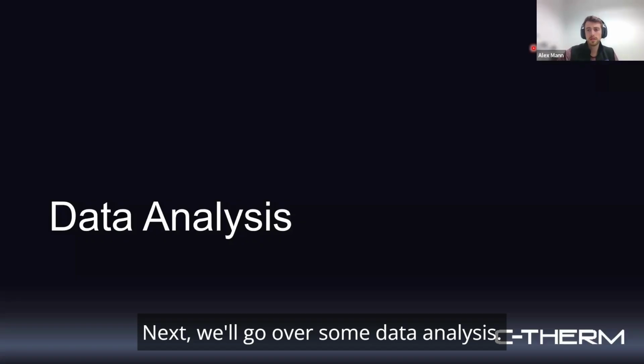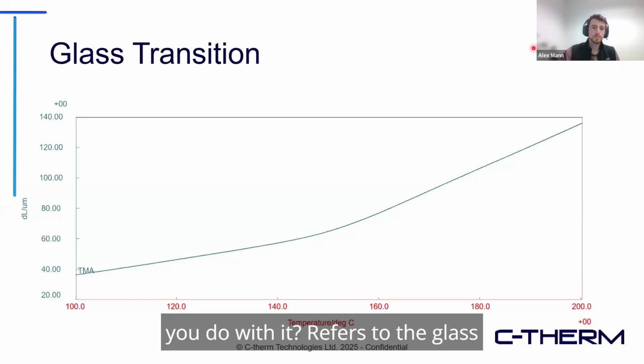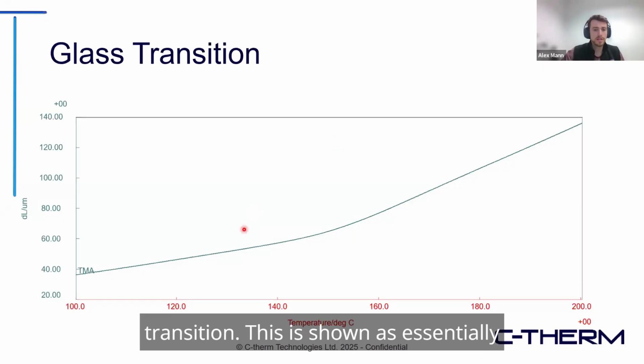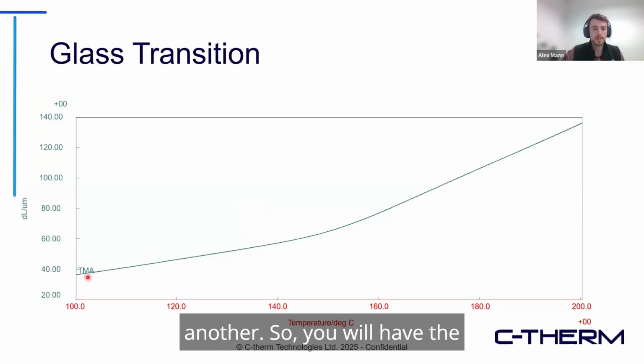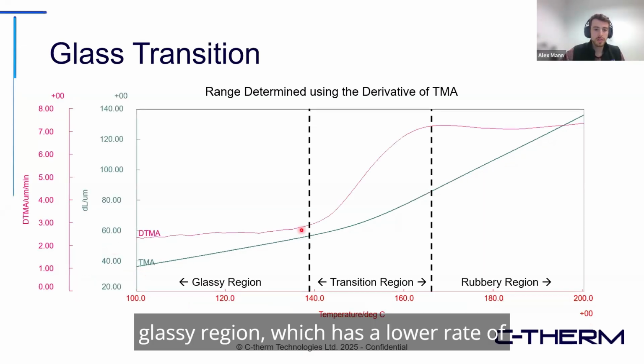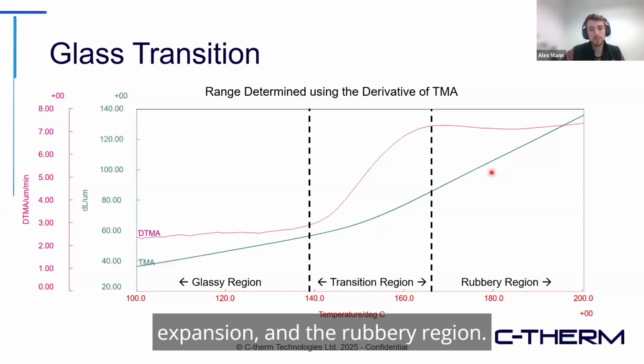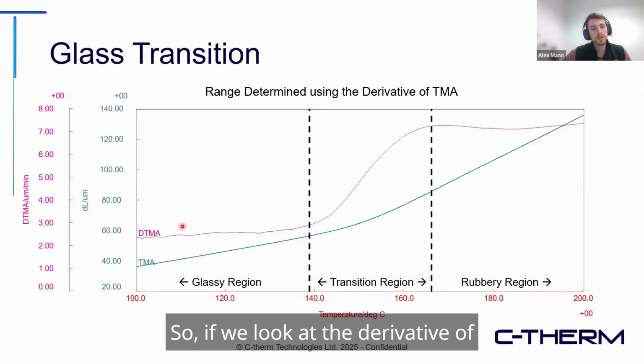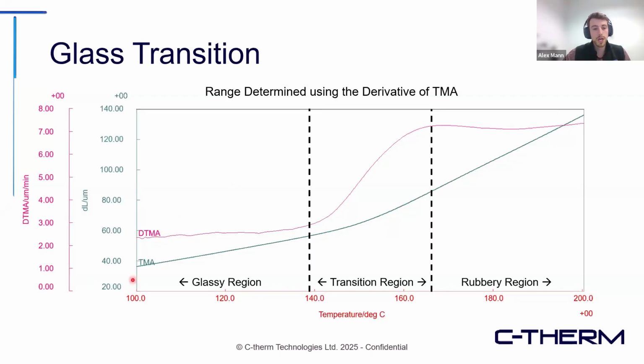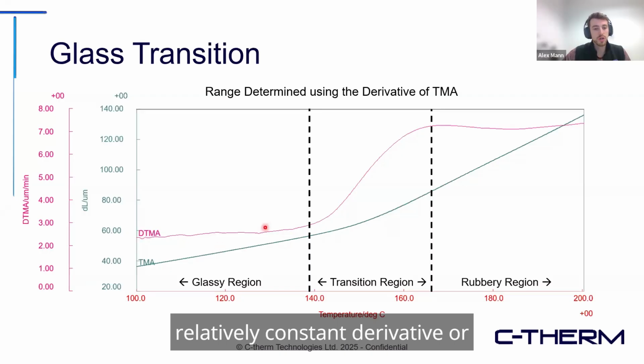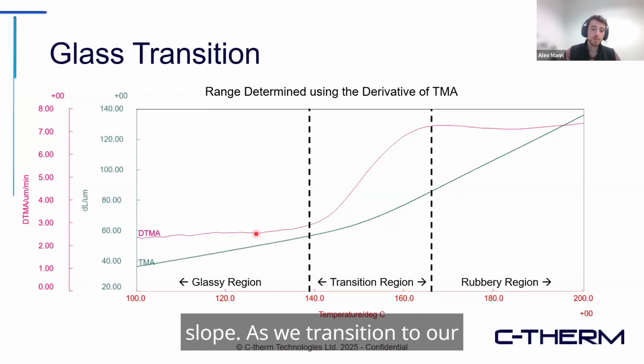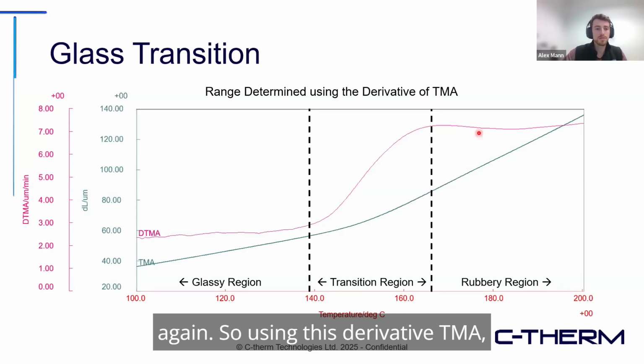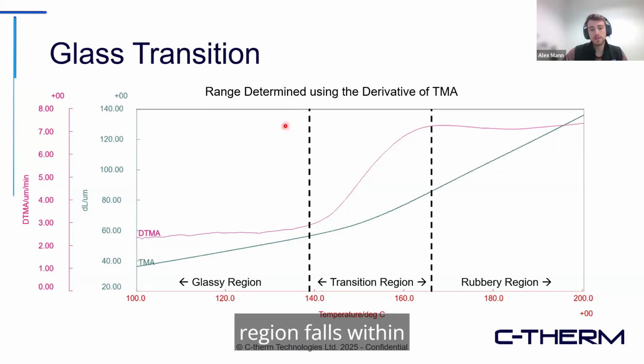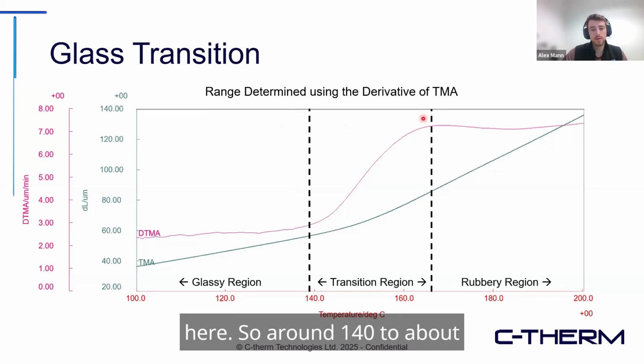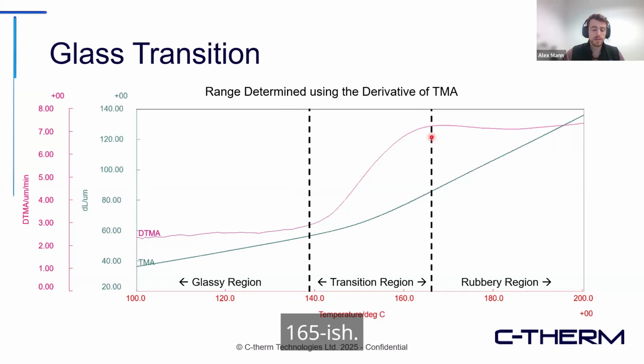Next, we'll go over some data analysis. You have your chart. What do you do with it? First is a glass transition. This is shown as essentially two straight lines that curve from one to another. So you will have the glassy region, which has a lower rate of expansion, and the rubbery region. If we look at the derivative of TMA, so the rate of expansion, we'll see this is a straight line. So it has a relatively constant derivative or slope. As we transition to our rubbery region, the derivative changes till eventually it flattens out again. So using this derivative TMA, we can determine that the transition region falls within here. So around 140 to about 165-ish.